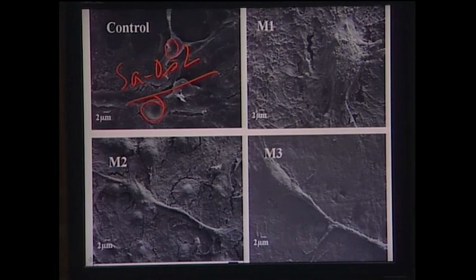These cells form a cellular network, with extensive filopodia extension. This is one cell, this is another cell, and this is filopodia extension from this cell and from that cell, and there is a cellular bridge formation. And as you can see, there is some collagen-like layer formation, that is, ECM formation, in these materials when they are seeded for 24 hours.